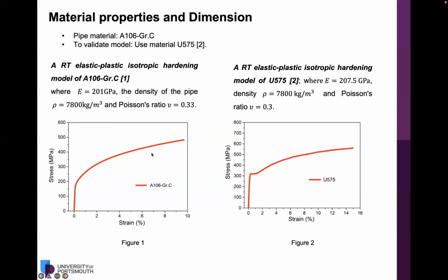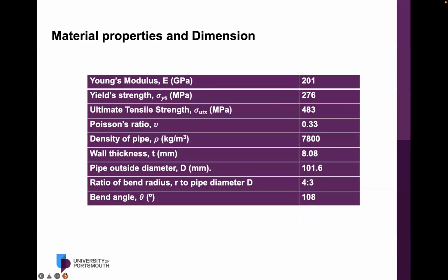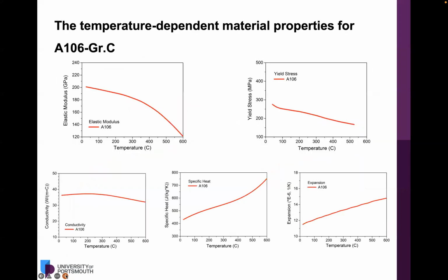The results or the readings of the properties are more or less similar or in agreement. There is some more information on the material properties listed in this table, as well as the dimensions of the pipe for our models. We are also referring to the temperature-dependent material properties of the A106 grade C, such as the elastic modulus, yield stress, conductivity, specific heat, and thermal expansion. They are all a function of temperature.